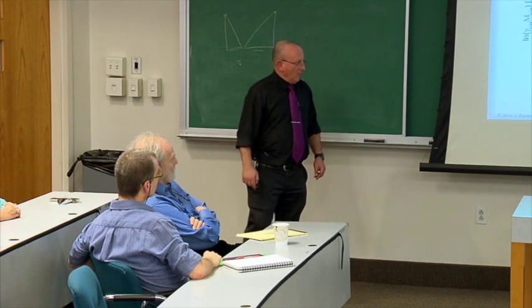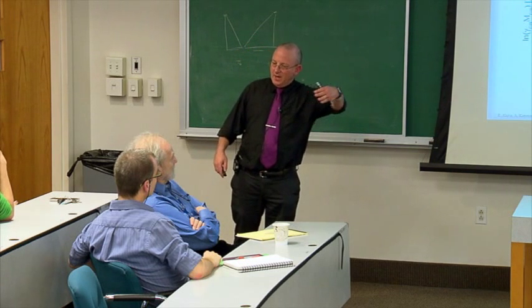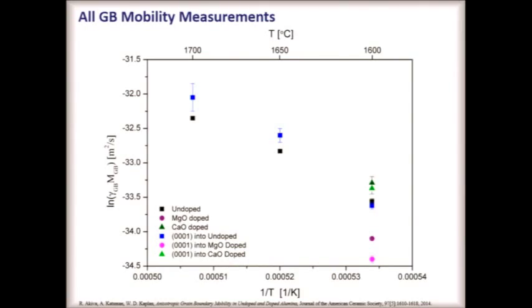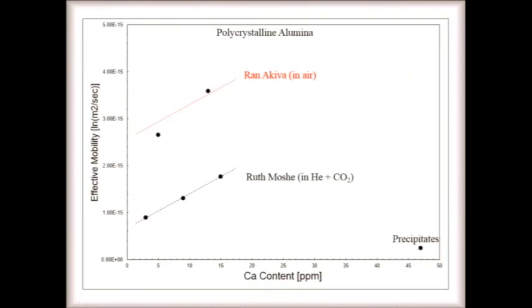By the way, it works out that way for the single crystals, the basal plane, the same thing. This is now color data showing the single crystal growing into the undoped or the magnesia doped or the calcia doped, and it works out exactly the same. Okay. Yeah? Why drop off the change point in your data for calcium? Well, what do you think is causing the elongated growth, and why does that change your fit?